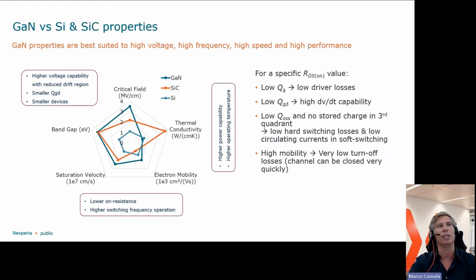Quite a nice way to show the properties of gallium nitride, doing a comparison versus silicon carbide. And if you translate the physical characteristics of these compounds into a rather easy diagram, as you can see, you can note that you have a critical field and a higher band gap for the gallium nitride. So at the end, it's translating into higher voltage capability and smaller QGD. So you have a smaller device, so you increase the power density.